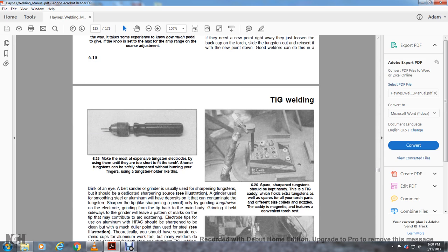A belt sander or grinder is usually used to sharpen the tungsten, but it should be a dedicated sharpening source. The grinder should not be used on steel and aluminum, which will leave deposits that can contaminate the tungsten. Sharpen the tungsten tip like sharpening a pencil, grinding lengthwise from the tip to the back, not held sideways. Grinding sideways will leave patterns and marks on the tip that may contribute to arc scattering. The electrode tip used for aluminum with AC should be sharpened to a clean but much duller point than for steel.